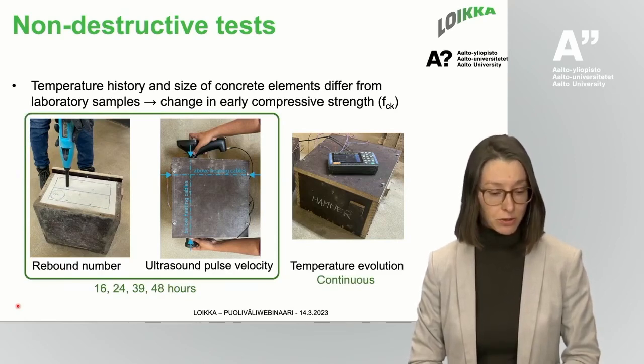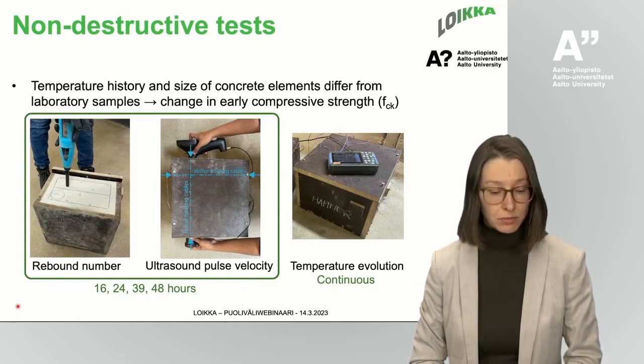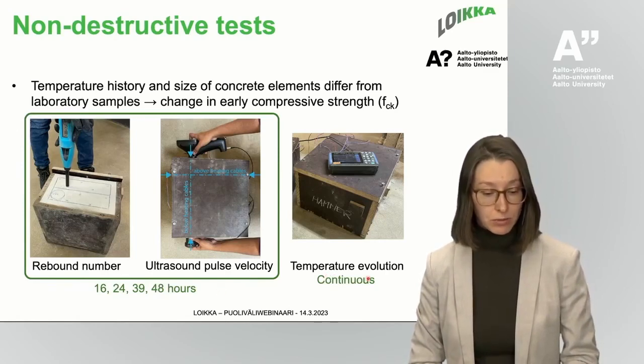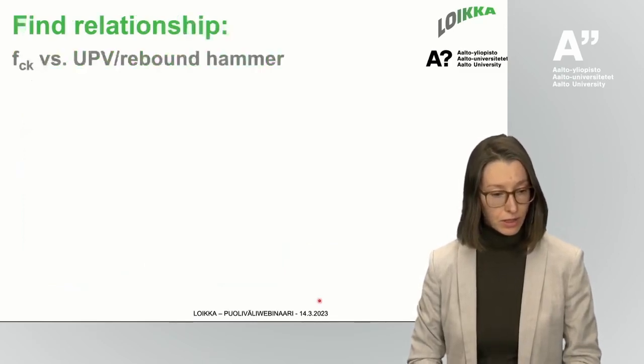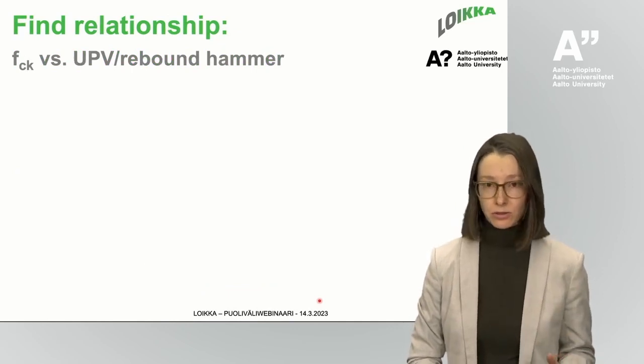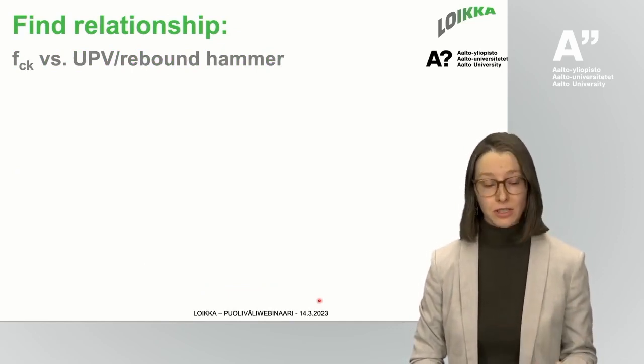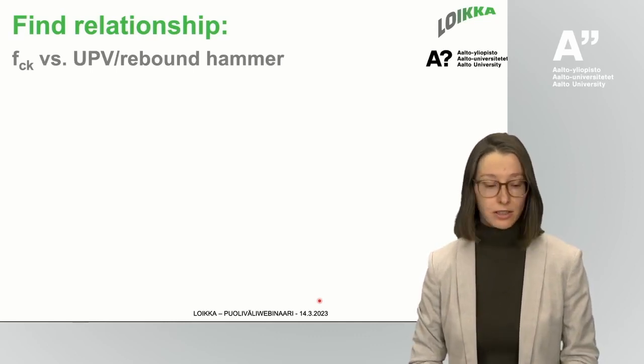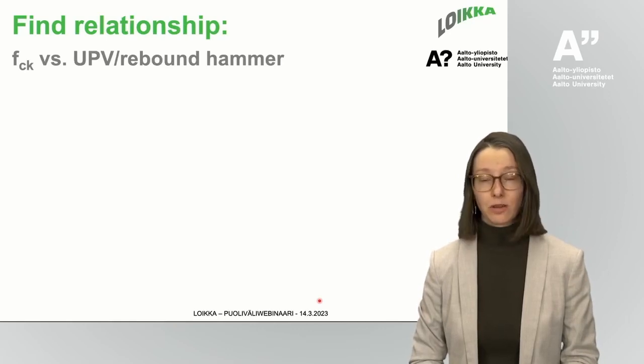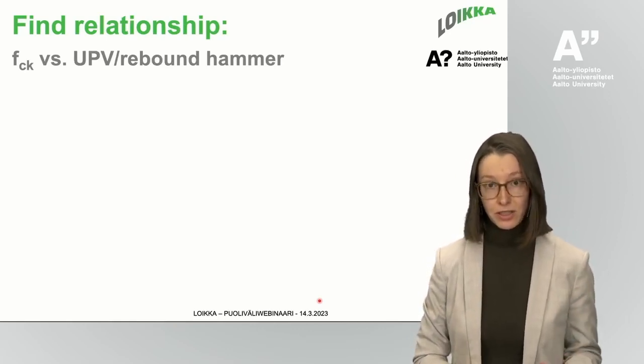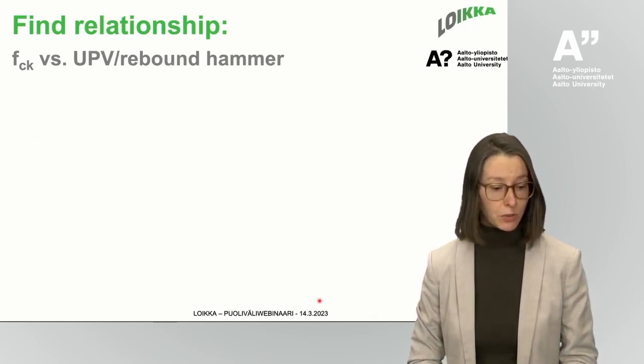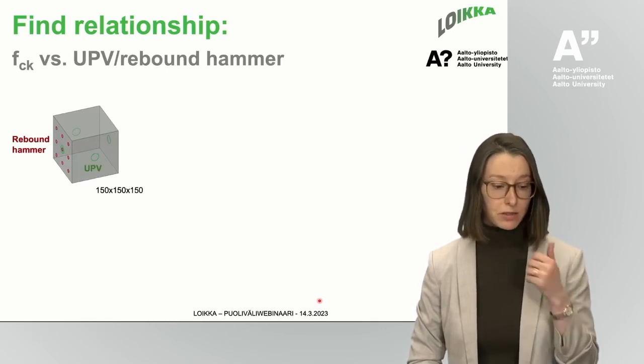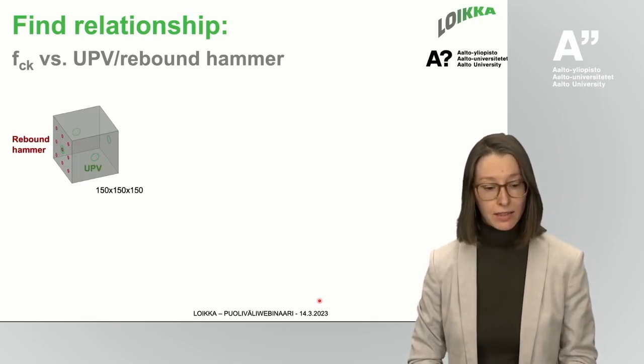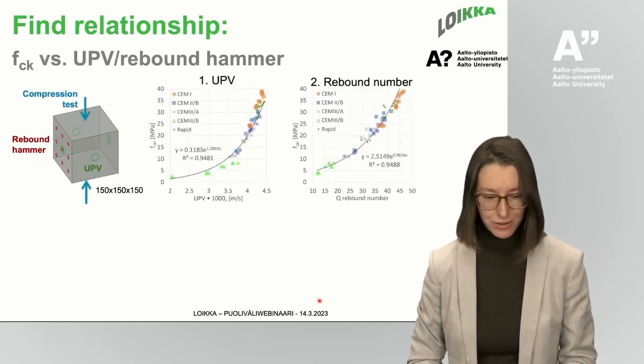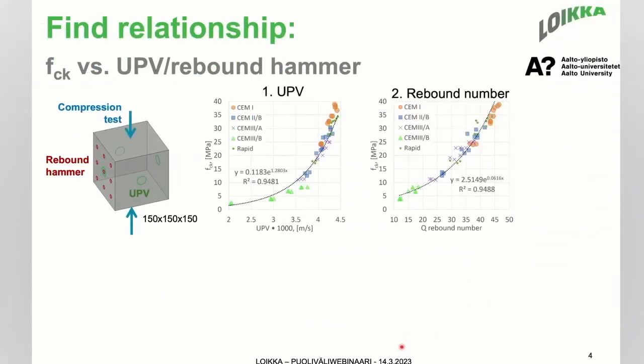We measured these samples during first 48 hours for early strength development, and also during that time, we measure temperature evolution. So because the rebound hammer characterize mostly the surface and UPV characterize mostly the inner characteristics, as Anna said, we decided to find the relationship between non-destructive methods and destructive methods. For that purpose, we took the samples and measure for them rebound hammer and UPV, and then made correlation with the compressive strength. Since they characterize different surfaces, it was logical to combine them.